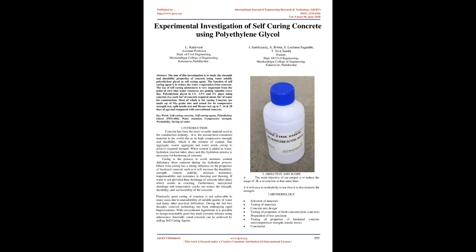Curing is the process to avoid moisture content deficiency in concrete during the hydration process. Curing has a strong influence on the properties of hardened concrete, such as increasing the durability, strength, volume stability, abrasion resistance, impermeability, and resistance to freezing and thawing. If water is not provided, then shrinkage of concrete takes place, which results in cracking.